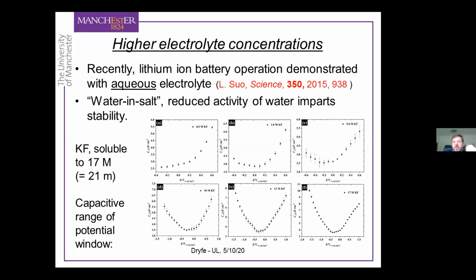And they use some organic solvent at very high concentration, I think about 20 molar. But we found that some of the simple alkali metal halide salts are actually soluble to almost those concentrations. For example, potassium fluoride, which is the salt that Graham used for a lot of his work on mercury in the 1940s, is in fact soluble in water at room temperature up to 17 molar. So we started looking at the capacitive response of graphite electrodes, basal plane graphite, as a function of KF concentration. And here are the graphs.